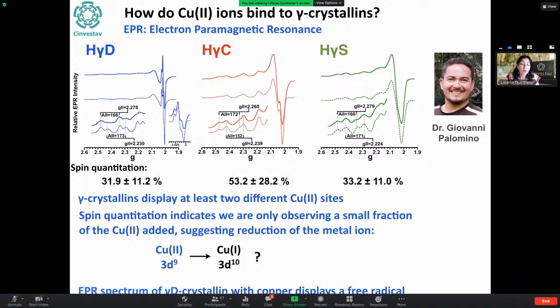Well, we thought maybe it's getting reduced to copper-1, forming a 3d10 configuration. So then this will no longer be paramagnetic, and will no longer contribute to the spectrum. Also in the gamma D spectrum, he could see a very stable free radical here, and I'll talk more about that. So these two things suggest there's some redox chemistry going on.